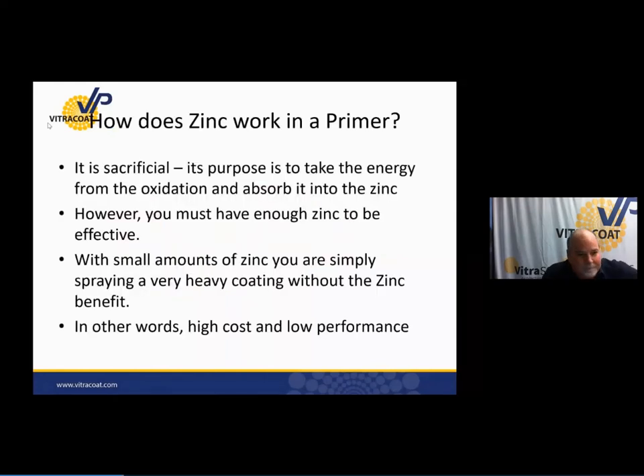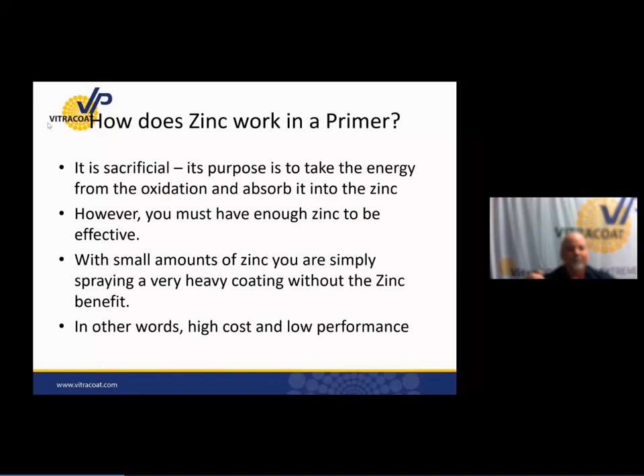Here's the reality. First, you have to understand what the zinc is doing in the primer. The zinc is sacrificial. Its purpose, it's a hard word to say, is to take the energy from the oxidation and absorb it in the zinc. However, and this is a key element, you must have enough zinc to be effective. Small amounts of zinc are simply spraying a heavy coating without the zinc benefit. If I'm putting a very small percentage of zinc in the coating, I'm getting little to no benefit from the zinc and how it's supposed to function.